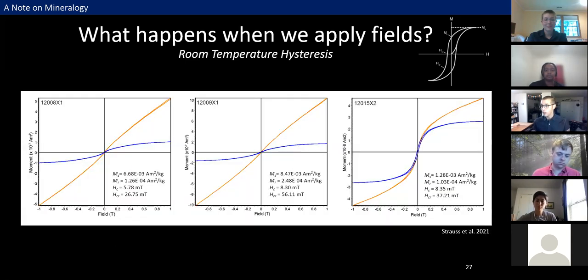So here are three representative subsamples that we ran these analyses on. On our x-axis, we have the applied field in Teslas, and on the y-axis, we have our magnetic moment. And you can see our raw data in orange and corrected data in blue. So I've also pulled out some coercivity and magnetization parameters, which are typically used to define the shape and size of each loop. And this is what lets you start comparing samples to each other.